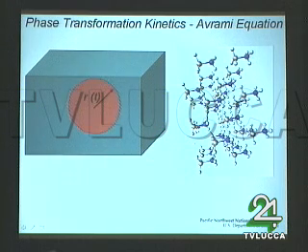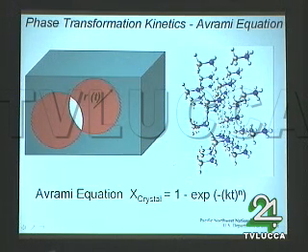And I think, so here's, whoops, I did that too fast. So you get this nucleation site that happens, and it starts to grow. And if you get a nucleation site somewhere else, they overlap. And once they start overlapping, that's when the reaction starts to go down, because you have these depleted areas of hydrogen. And they introduced me to the Avrami equation.